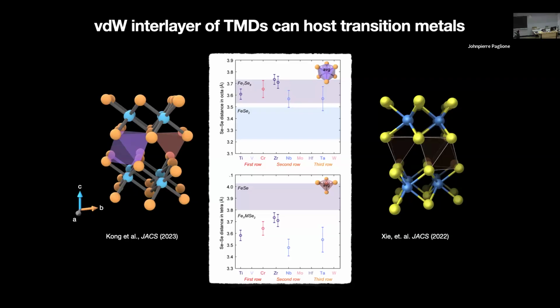So if you compare the size of, let's say, a selenium-based ligand field or crystal field octahedral site, you'll see that in the zirconium case, for example, or even across the row, for all the metals, the size of that interstitial region is comparable to the size of the octahedral sites in bulk iron chalcogenide compounds.